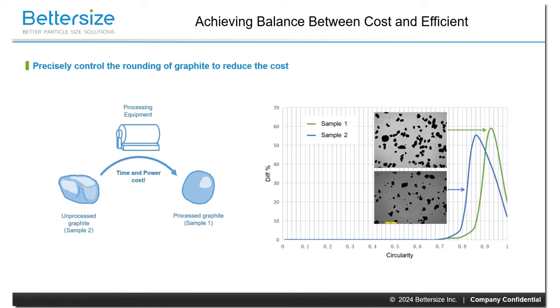The dynamic image analysis can help accelerate circularity measurements with its high efficiency and provide us with a robust way to measure particle circularity. This method is fully in accordance with the standard also. From the particle shape distribution on our right, we can find that sample 1, after processing, the particles are more rounded than sample 2, which is unprocessed.